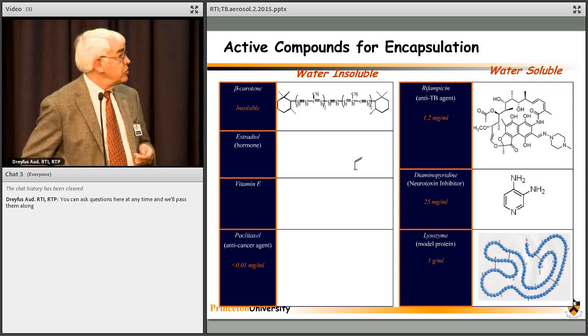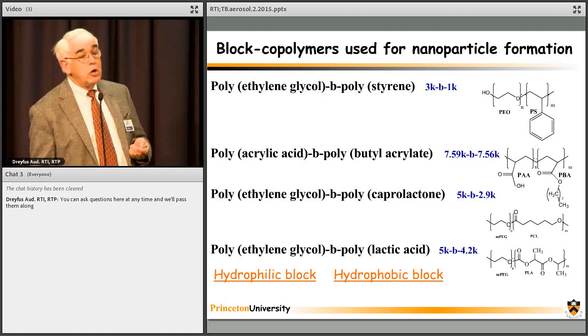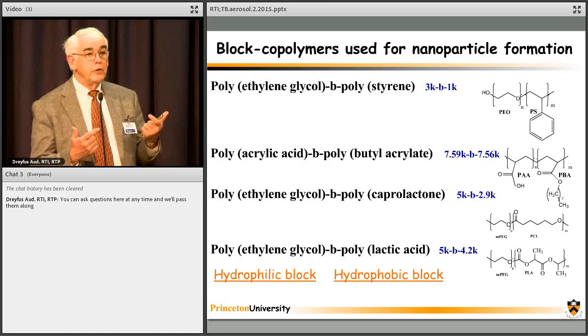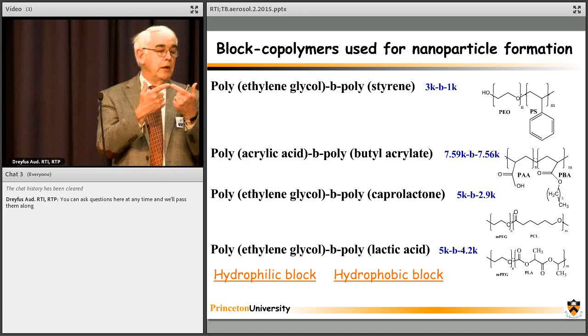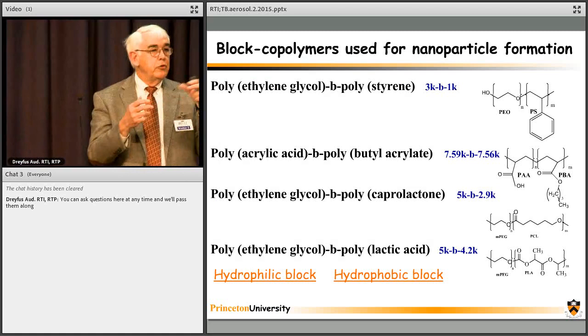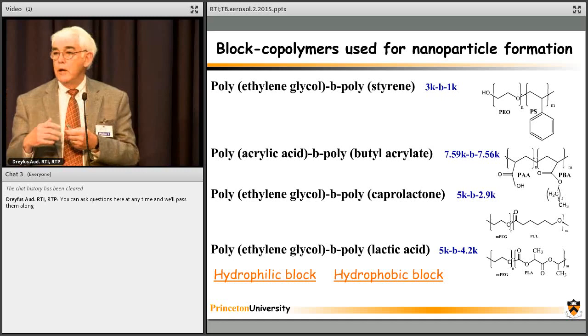It's not chemically specific. Here are the block copolymers. We can use lots of different block copolymers because it's not really a chemistry issue. It's polymer physics. So what do we want? We want a hydrophobic end that's big enough that it stays anchored. We want a hydrophilic group that's big enough that it provides a dense steric layer that prevents protein adsorption, because that's how most clearance occurs, by protein adsorption and then opsonization. The system recognizes this as something that a protein is stuck to and is supposed to be cleared.